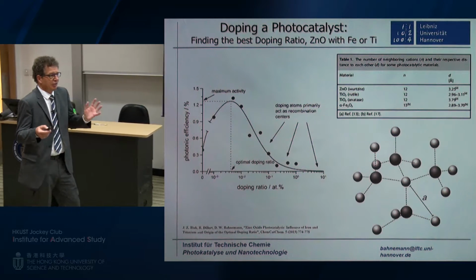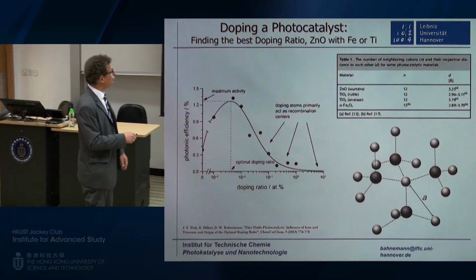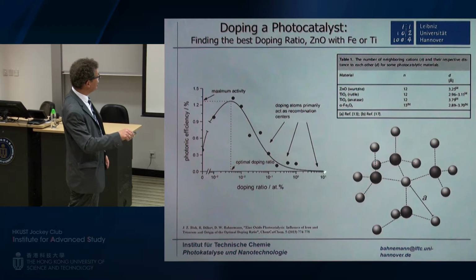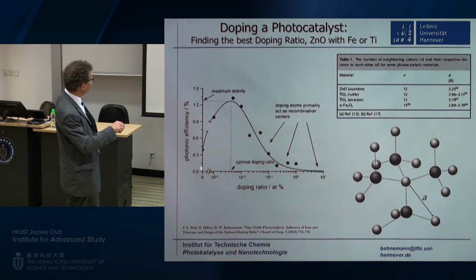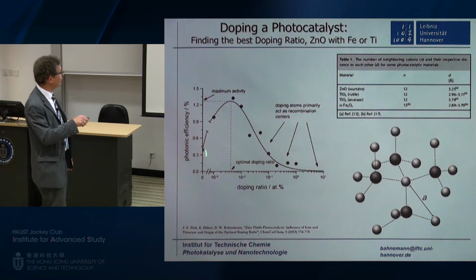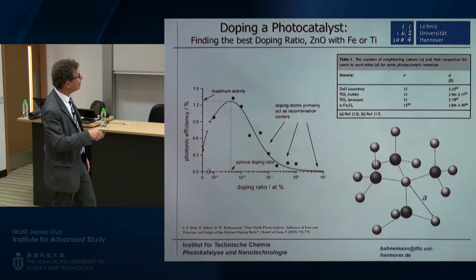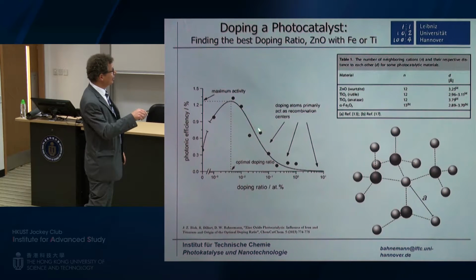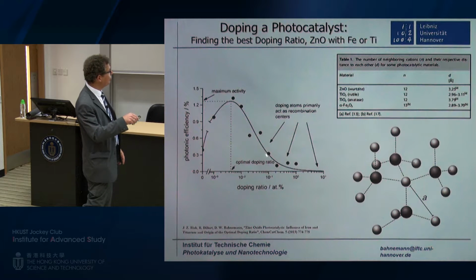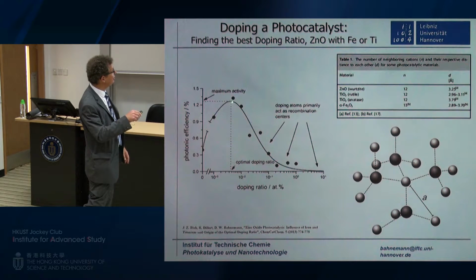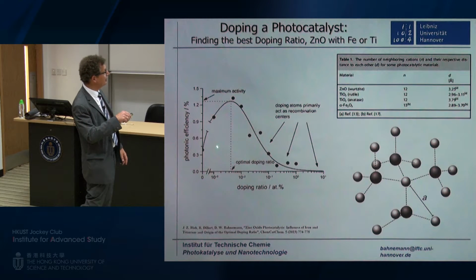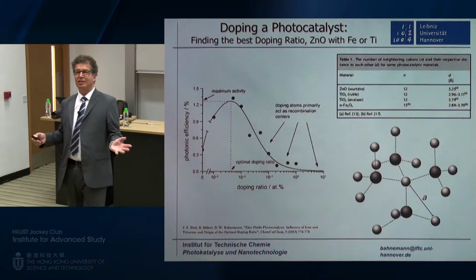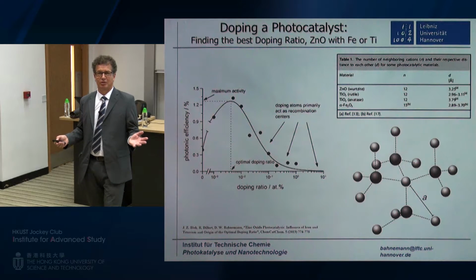That was our second assumption, and doing this you can get pretty nicely a dependence of the activity versus the doping ratio. The activity is on a linear scale and this is a logarithmic scale. And this was our prediction of this simple-minded model. And these are the data points shown in the last slide. So the simple-minded model works.